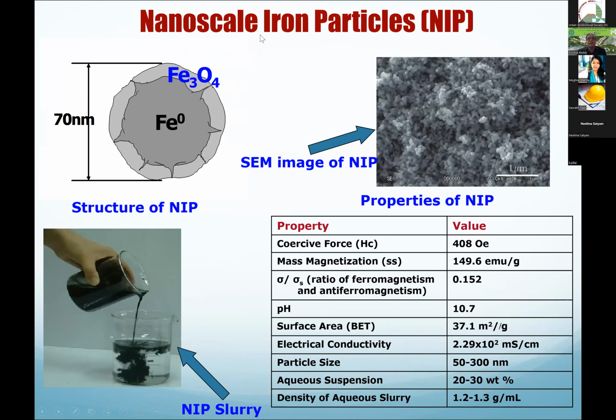Okay, so this is the study we did because the Japanese company was interested in creating a new market for their nano iron particles. They also supported our NSF project as an industrial sponsor, and we were able to get these nanoscale iron particles from them. So we didn't really synthesize them, but we used the commercial ones. You see this 70 nanometer is the average size.